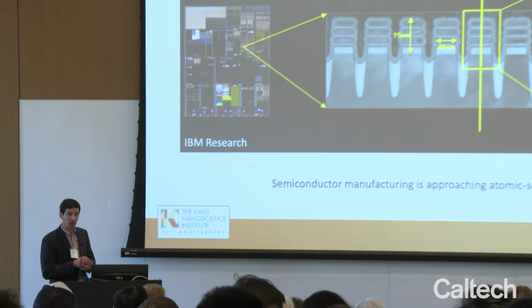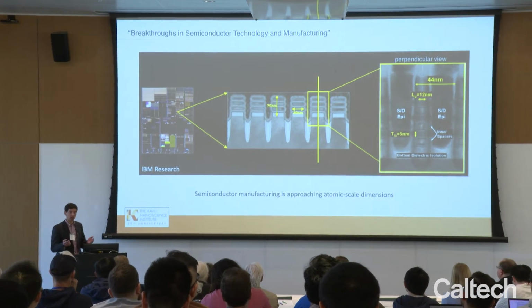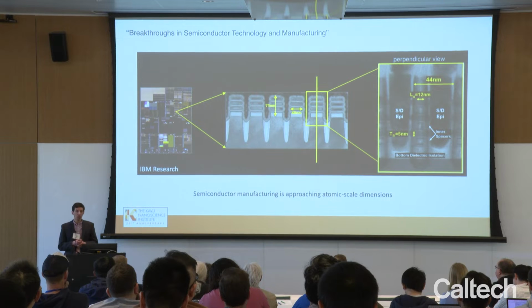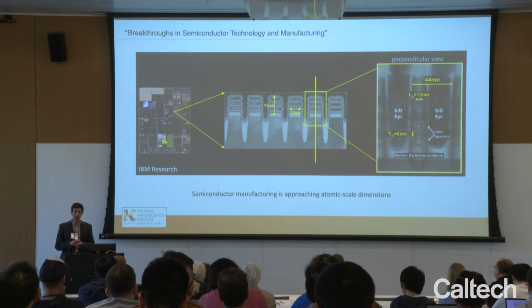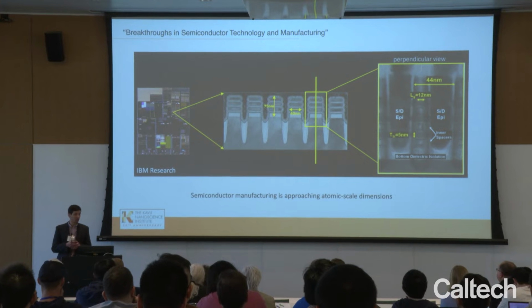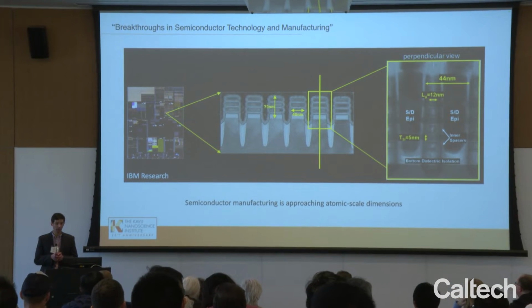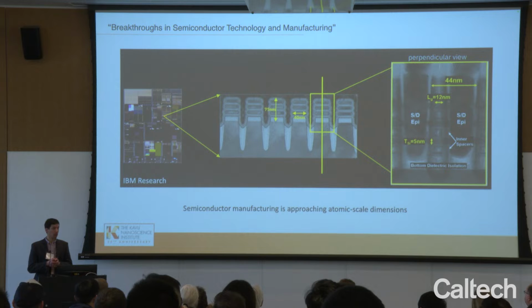This is just an image of a gate-all-around field effect transistor, which is modern technology at this point from IBM. If you look at the right side of the image, the critical feature dimensions are on the order of 5 nanometers and getting towards single-digit nanometers. At some point, you'll be limited by the interatomic distance of atoms in crystals, which is going to be 5 to 10 angstroms, so 1/2 to 1 nanometer. And we're interested in ways that we can manufacture these microelectronic devices reproducibly over wafers at this scale.